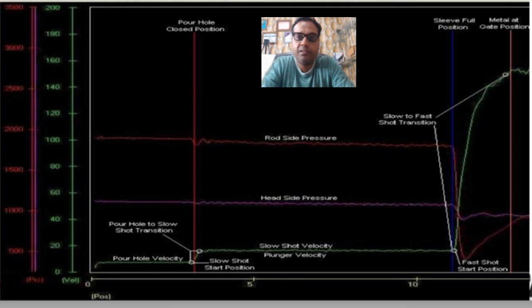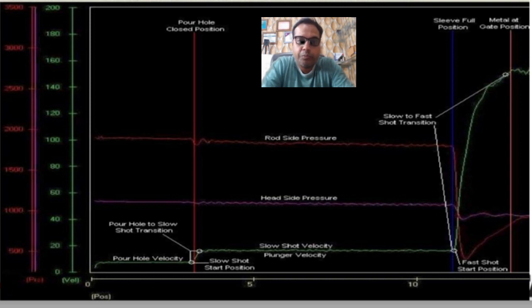The next process parameter is fast shot start position. At the sleeve full position, the cold chamber die casting machine should initiate the fast shot. The means to control this position accurately is to have accurate closed-loop measurement of position by the PLC. When the desired start position is achieved, the PLC should trigger the fast shot to begin. When using PLC position-based shot control, the normal PLC scan should be interrupted so that timely control of the position-based output may be completed; however, this interruption should not be higher in priority than the safety functions of the die casting machine.